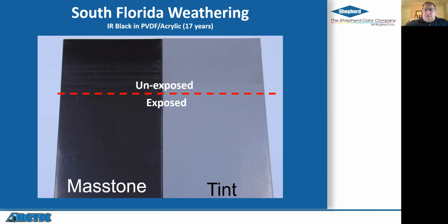And so this represents what it would look like if it weren't exposed to the sun, and this is exposed to the sun. As you can see in this high performance resin system, these high performance pigments are giving durable, lasting color. This infrared reflecting property is inherent in the pigment chemistry. It's not an additive or anything like that, and it doesn't wear out over time. So the reflectivity that you get initially is inherent with a pigment and will be there for years and years.